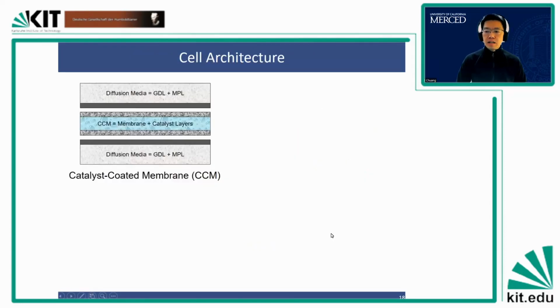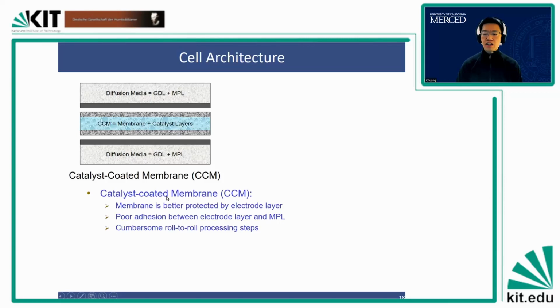Okay. In the last project before I left General Motors, I worked on different cell architecture. If you take a look at this, you have the membrane and then the catalyst layer. And then here you have the gas diffusion layer, which has GDL and MPL, which is separated. Right? So this has a lot of advantages. The membrane is better protected, but it has poor adhesion between the electrode layer and the microporous layer, and it also has cumbersome roll-to-roll processing steps.